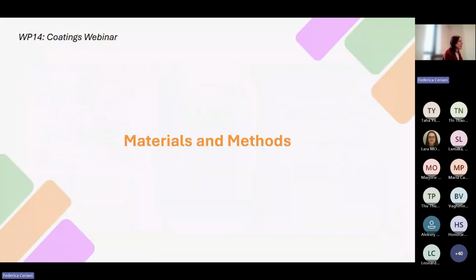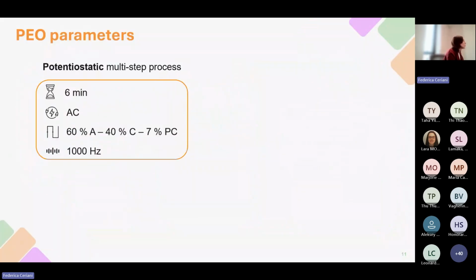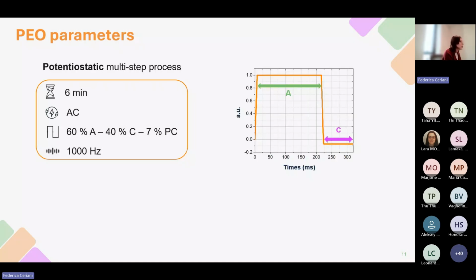Let's move to the materials and methods, starting from the PEO parameters. I perform a potentiostatic multi-step process with a total duration of around 6 minutes. I work in alternate electrical regime, applying a waveform consisting of a duty cycle of 60% anodic, 40% cathodic, with a cathodic peak having a magnitude equal to 7% of the anodic value. This duty cycle is applied with a frequency equal to 1000 Hz.